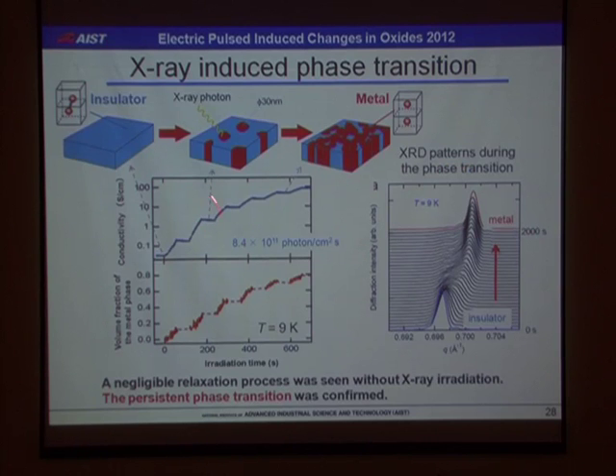So we explored the transition dynamics in detail. Here is the experiment at low temperature. The conductivity and volume fraction of metallic phase are plotted as a function of irradiation time. Here, X-ray is intermittently off, as indicated by this dashed line. Actually, this volume fraction was calculated from this XRD peak. The original line is this insulating phase, but it is converted to the metallic state by irradiation of X-ray.